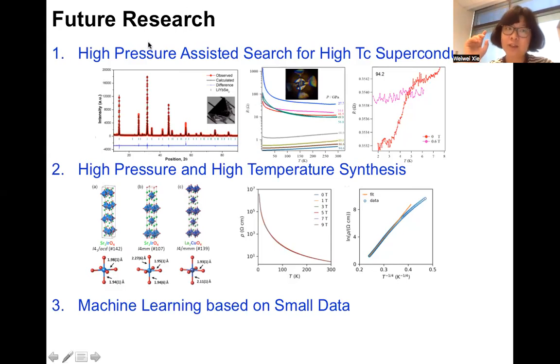For example, we are using high pressure as assistance to search for high Tc superconductors. Here we have an example, also LiYbSe2. We made the new material at ambient pressure, and then pressed it under high pressure and studied the resistivity to see if it is a superconductor. LiYbSe2 itself is a very good quantum spin liquid candidate. It is an insulator with a huge band gap. By pressurizing it, we close the band gap, and around 100 GPa, which is very high, we see a superconducting signal coming out. This is very cool.